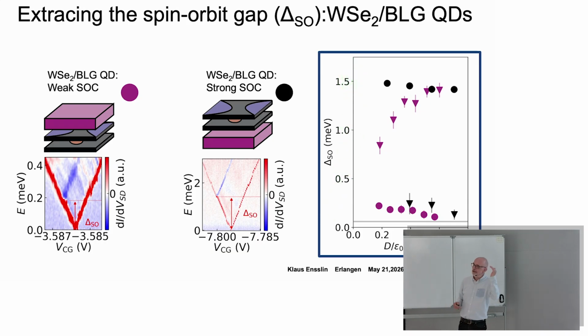So you have gone up by a factor of 15. If you compare it to the TMD, the spin-orbit was 500 milli-electron volts. So you have come down a factor of 500 from the TMD, and that's the exponential tail of the wave function that penetrates into the graphene. Okay. And now you have a parameter that you can tune. I think that's something very new, that spin-orbit interaction is not simply a parameter in your system, but you can tune it over orders of magnitude.